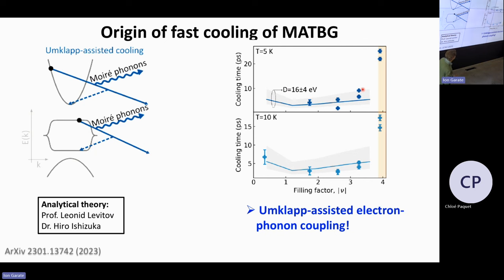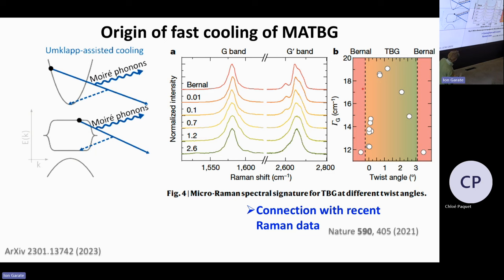And at high temperature, what they predict is actually that the number will be the same. So that's very much consistent. So what we believe is that this actually explains some results that were published just a few years ago in Nature, where they saw that for angles deviating from 0 degree and then going up and then towards 3 degrees, it's already down again, you have a broadening of a certain Raman mode. And they ascribe this to strong electron-phonon coupling. So with strong electron-phonon coupling, you get a broadening of this mode, and it happens somewhere around this kind of magic angle around 1 degree. But it's not as critical, this angle, as it is for superconductivity.